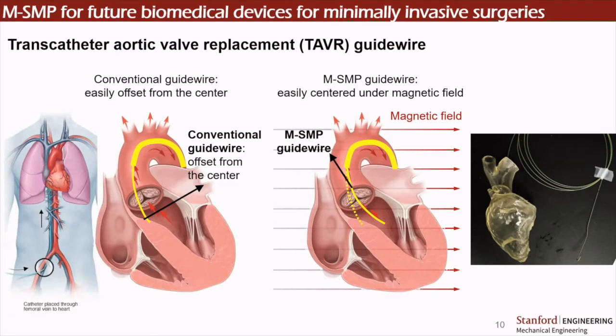So with the new magnetic membrane polymer, we can actually easily tune its rigidity, and still have a fully functional guide wire. In the very beginning, at body temperature, it's really stiff and it can prevent any type of buckling when it goes to the heart. And once it reaches the heart and needs to make this 180-degree turn and be centered, we can easily apply an external magnetic field to soften it, basically increase the temperature, change the rigidity, and then we can use the actuation magnetic field to easily change the orientation of the guide wire to center it.